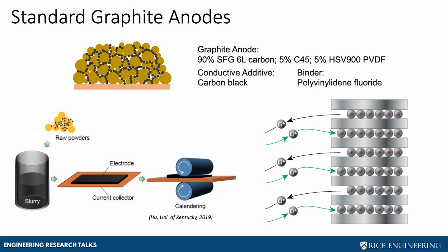Now, if you look at standard graphite anodes, how you process them is you take those active materials, you mix them with some type of conductive additive, some type of binder. So you're making what we call a slurry. Basically, it's like a paste. We're going to spread that paste on a current collector, like copper, and we're going to do some processing, and then we have our anode material on here. And what's nice about graphite is it's a layered structure, so lithium is able to intercalate. It fits into those layers very well.